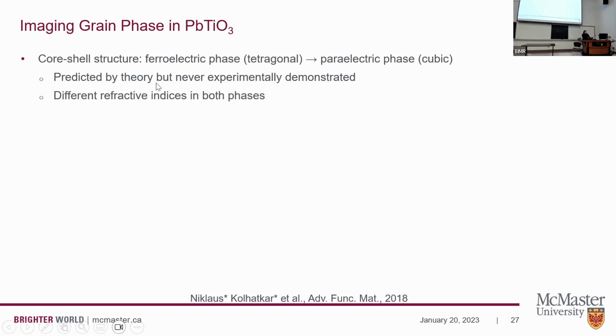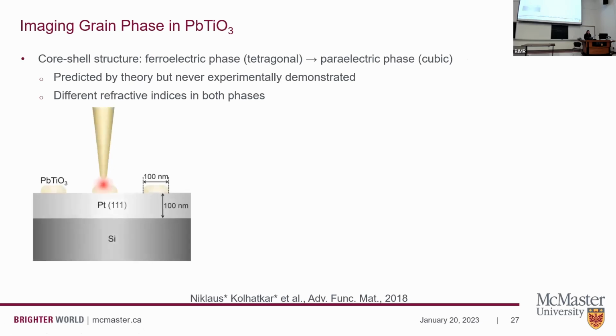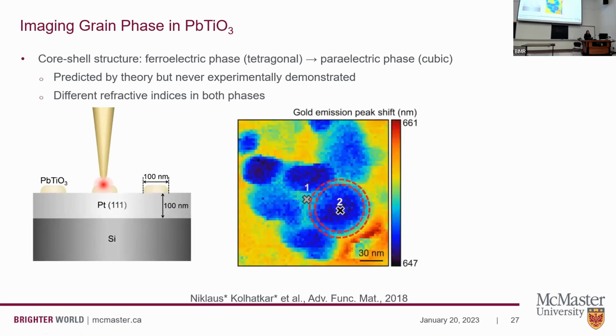These lead titanate nanoislands have been predicted to have what we call a core-shell structure, where the core is in the ferroelectric phase, which means that it's in the tetragonal crystal phase, while the shell will be in the cubic phase. Both of these phases will have a different refractive index. So what we did now is that we took those nanoislands and we imaged them, this time looking at the shift in the gold emission. And we got the image that we see here.